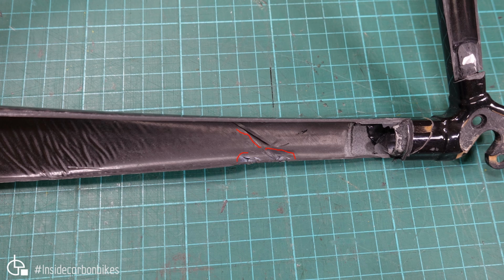Now the other thing that's odd is that on every other insert throughout the bike there was a glass barrier applied, but in this location there wasn't, and you can see that whitish residue is evidence of some galvanic corrosion, and the delamination is from the drilling process. So they could take a little bit more care there, and I'm not sure why they didn't put the glass barrier ply like they've done really well in other areas of the bike.